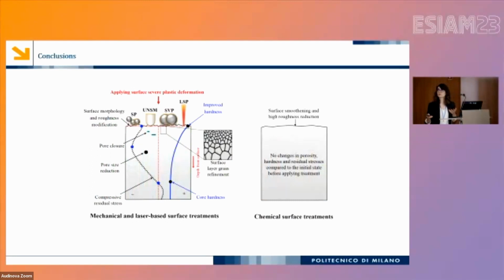Of course, the treatments that are based on severe plastic deformation can have pore closure effect. They reduce the surface roughness or homogenize, let's say, at least the surface roughness, depending on the treatment. And they are also inducing compressive residual stresses, while the ones that are based on chemical surface treatments are just not interfering, let's say, with the bulk material, but just changing the surface morphology.